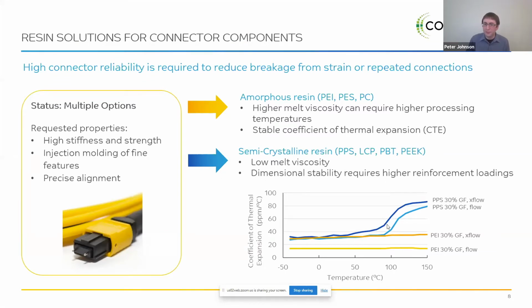And what we're showing here is coefficient of thermal expansion at the bottom. In the case of PEI, which would be an amorphous resin, the Ultem resin in particular, the coefficient pretty much stays constant across this temperature range we're showing. With something equivalent, say like a PPS, once you start reaching certain temperatures, it can start deviating. So it really depends on what your operating window is and how the design actually works. If you need something that's more robust, you might have to go one way or another. It really just depends on what you're looking for in the end.